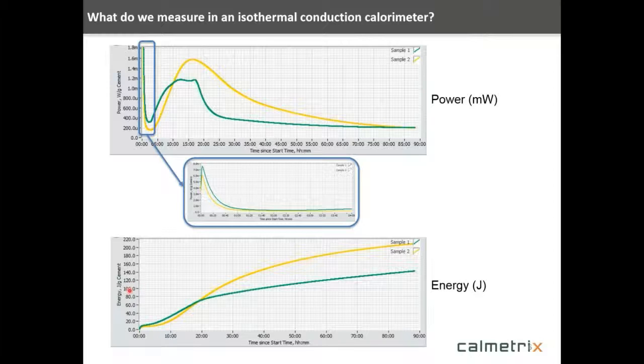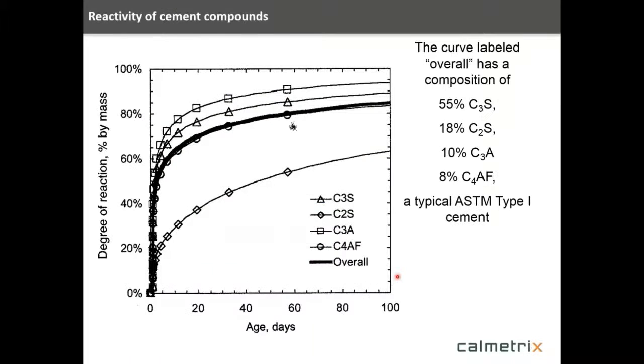So another type of curve that we look at are these continuous energy curves. So here we're plotting energy now in joules per gram as a function of time. And these are gradually increasing continuous curves. So at any particular point, this illustrates how much heat actually has been evolved from that sample over that period of time. So we use this data, we use both sets of data in the typical types of applications that we use the calorimeter for.